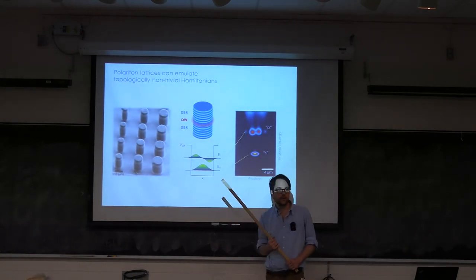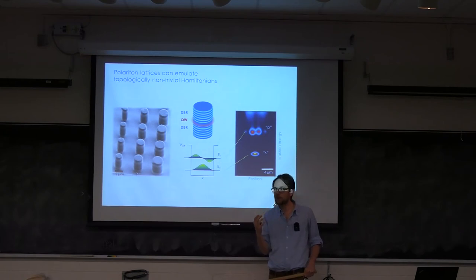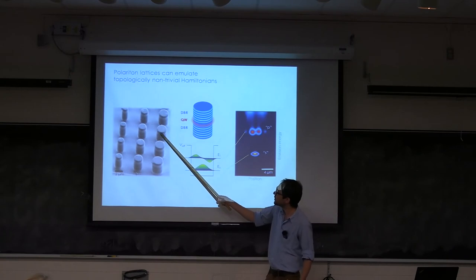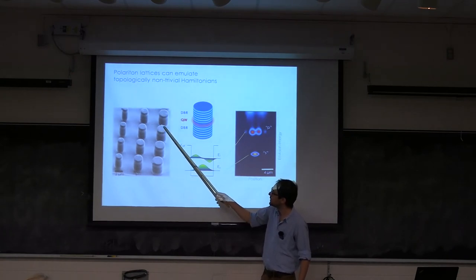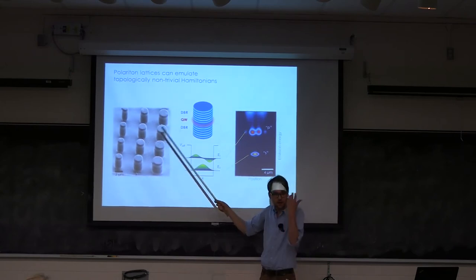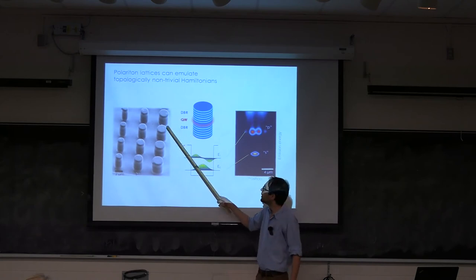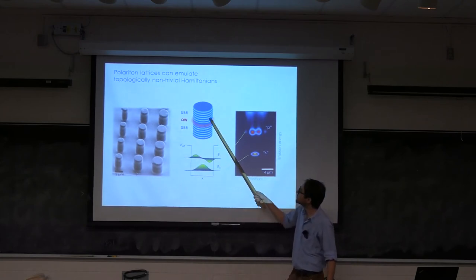So we usually rely on a tight binding approach, where the building block, or atom, is these pillars. These pillars are obtained by electron lithography and dry etching techniques. So what you see here is what remains from the cavity. Everything else has been taken out, and you end up with these cylindrical micropillars that are a few microns in diameter.